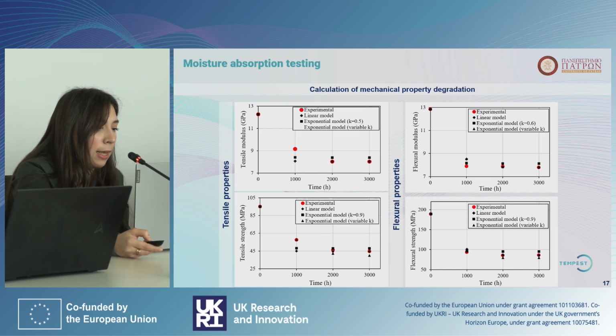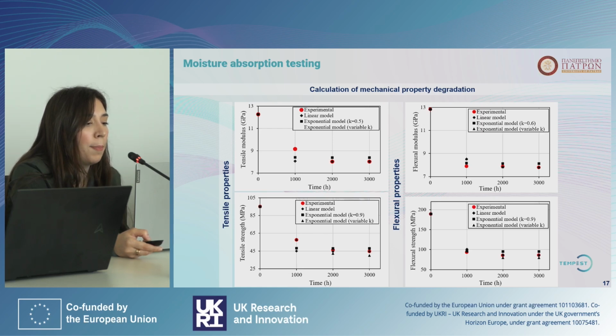We can see that in the tensile properties, especially up until 1,000 hours, there is some difference between the analytical and experimental results. However, this is due to the fact that tensile properties are fiber-dominated, while these analytical models are based on matrix-dominated properties.